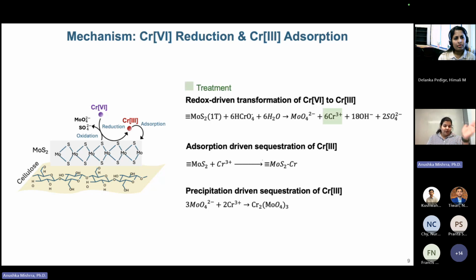So for the treatment purposes going forward, I'll show you some data we ran at scale. We're looking at chromium-3, but at the same time we want to be sure that the MOS2 is not a secondary source of contaminant, releasing molybdenum into the water that becomes toxic. So we'll be looking at both to see how this technology works for removing chromium-6 from groundwater.